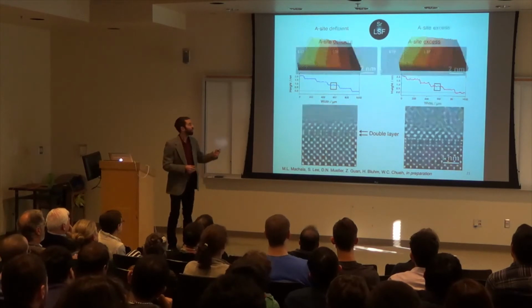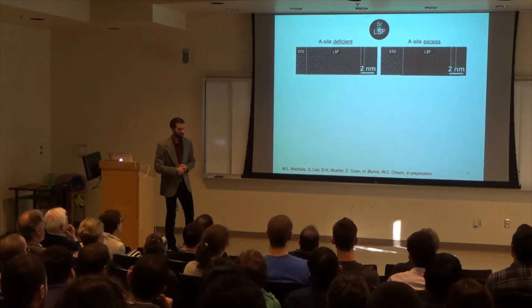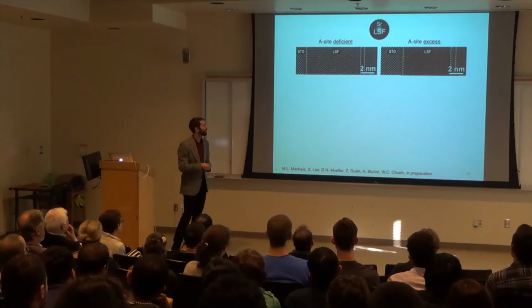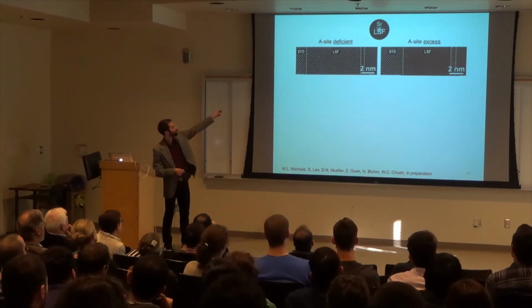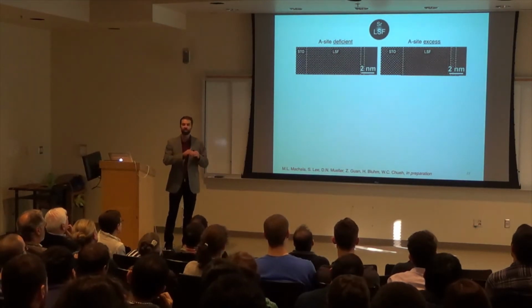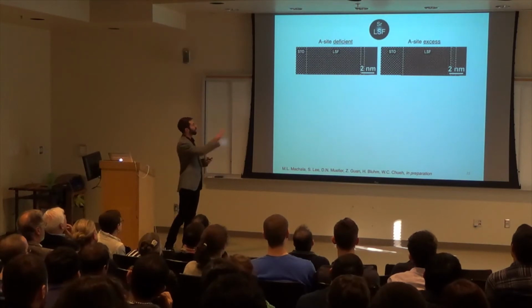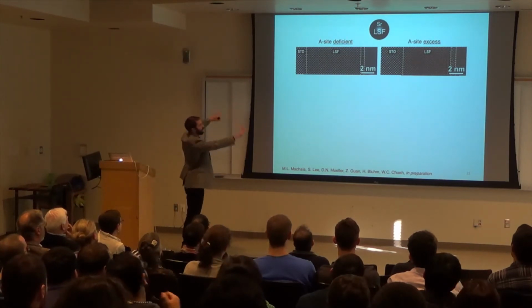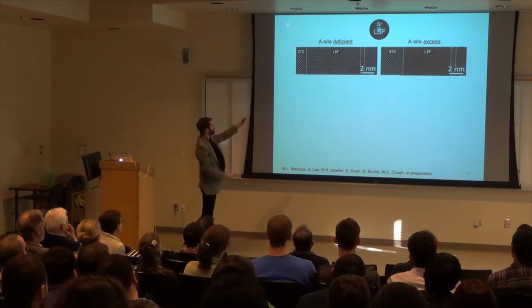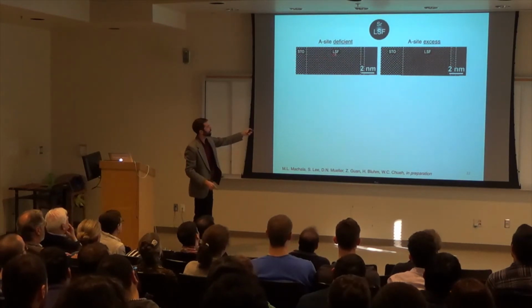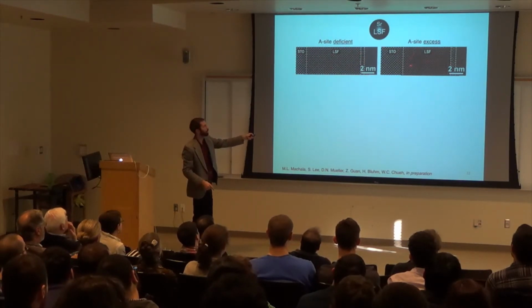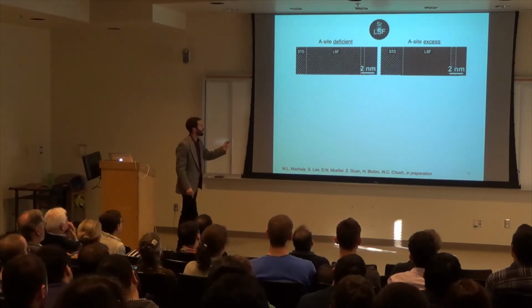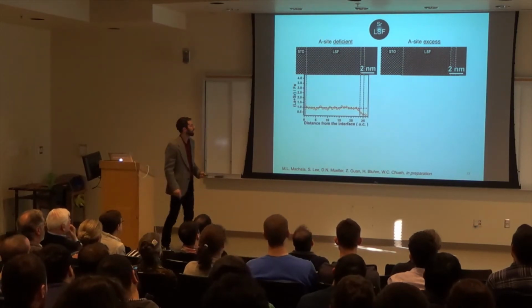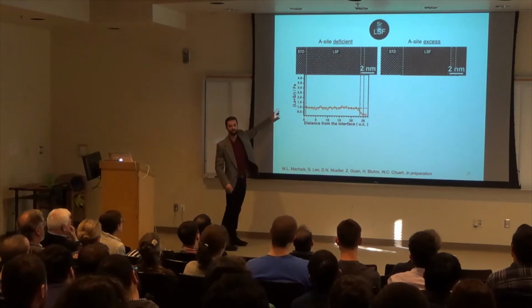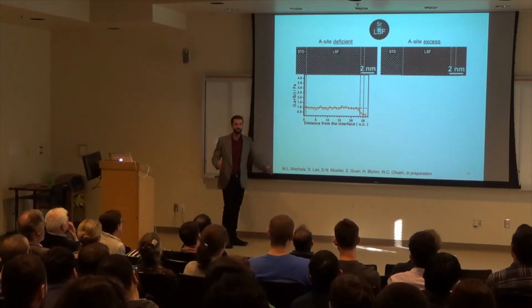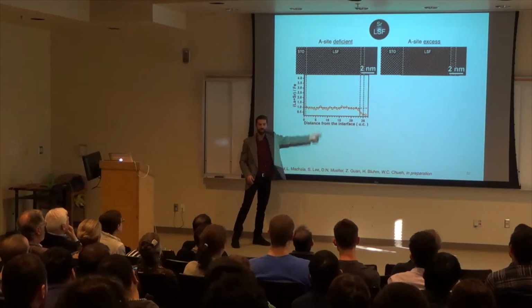To do that, we turn to the same measurement we did previously, where we do line scans going from the bulk to the surface, trying to do chemical mapping. And so here we have essentially those two images turned on their side, right? We have the substrate here, which is STO. We have our material of interest here, and we have the surface terminating on both sides. Okay? Now, the first graph I'm going to show you is basically the amount of A site relative to the amount of B site. And if they're equal, they're going to fall on this line here, 1.